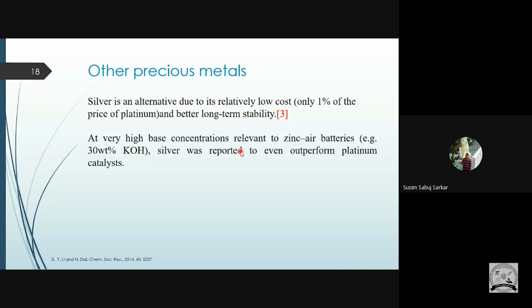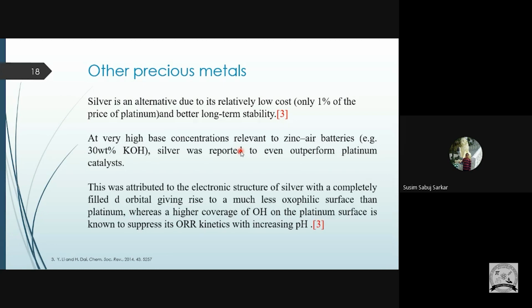Outperform in that sense means that it is more durable than platinum, and also sometimes gives more energy than platinum. Platinum can cause a side reaction or a parasitic reaction. In that case, platinum may not be more durable, and silver is the more durable catalyst. This is attributed to the electronic structure of silver, which has a completely filled d orbital, giving a much less oxophilic surface than platinum.